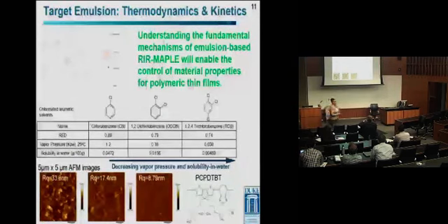And then just to give you an idea, we have developed this emulsion-based approach to RIR-MAPLE, so there are still a lot of fundamental questions about the mechanisms of the technique that we're working to understand. So for example, in that target emulsion, the thermodynamics and kinetics that control the emulsion properties, which we know has a direct impact on what the film properties are. Now one example, so this is just giving an example. So these emulsions, we have these emulsified particles of the polymer, so these polymer clusters, and the size of those polymer clusters has this impact on the film properties.